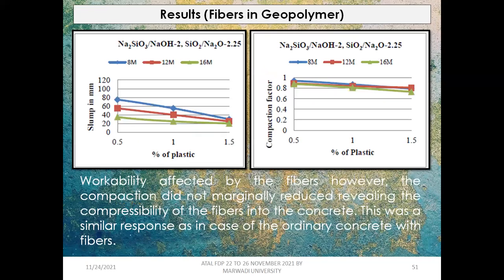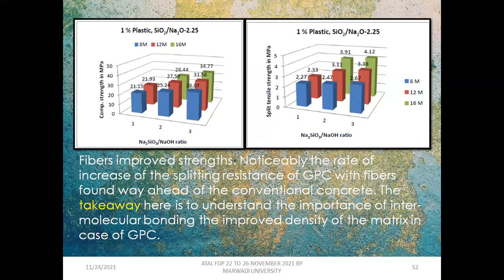Earlier, workability was affected by the fibers. However, this was expected, and it behaved in the same way, like the compressibility of the fibers in the concrete. This was a similar response as in the case of ordinary concrete itself. Then the fibers improved the strength. That's what we noticed. The takeaway is to understand the importance of intermolecular bonding and the improved density of the matrix in the case of GPC, that is geopolymer concrete.